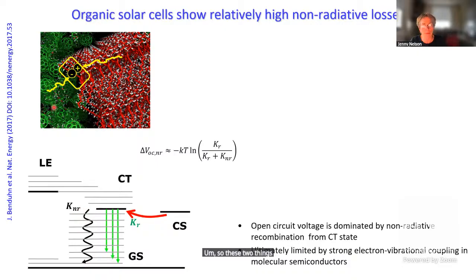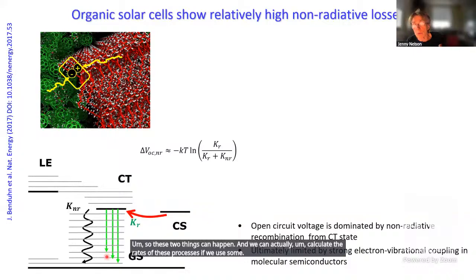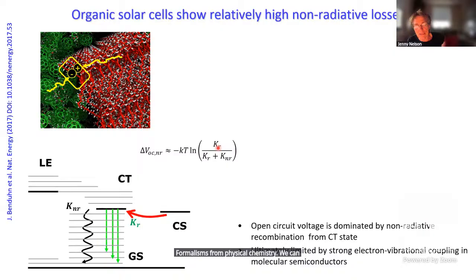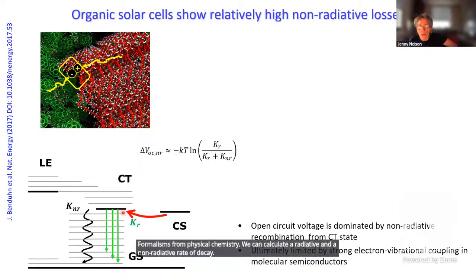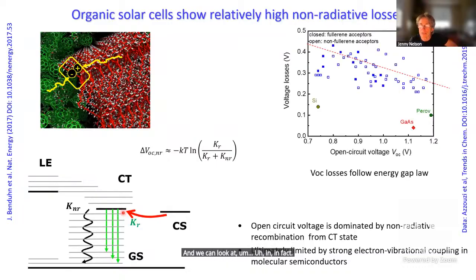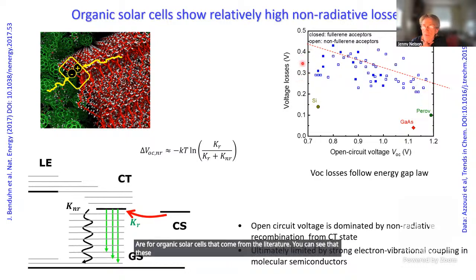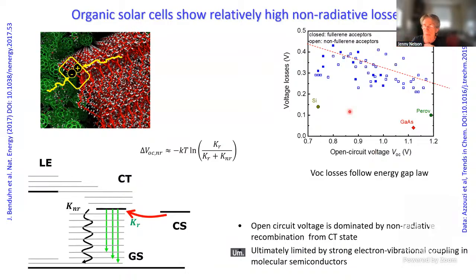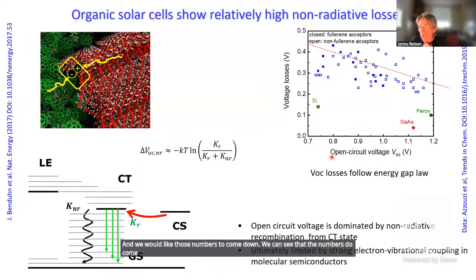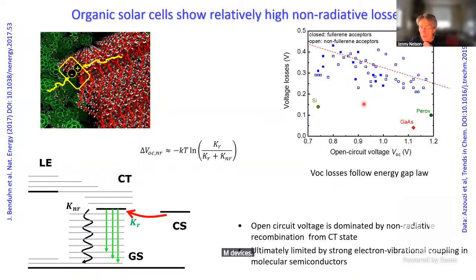So these two things can happen, and we can actually calculate the rates of these processes if we use some formalisms from physical chemistry. We can calculate a radiative and a non-radiative rate of decay, and we can look at how different materials perform. In this graph, I've collected some data showing the non-radiative voltage loss, and all these blue points are for organic solar cells from the literature. You can see that these numbers are relatively high compared, for example, to gallium arsenide or silicon or perovskite, and we would like those numbers to come down. The numbers do come down for larger bandgap devices, but still they're rather large.